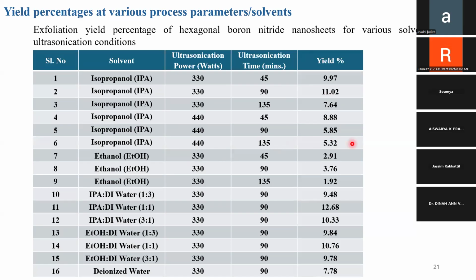At this stage, I tried to optimize the power, because I analyzed the results and found that 330 watts was giving me the maximum yield percentage. So we took 330 as the optimized power, then did further experimentation with 45, 90, and 135 minutes of ultrasonication time, and I got these as the yield percentages. You can see that it is very low. So I understood that incorporating ethanol as a solvent won't give a better yield percentage.